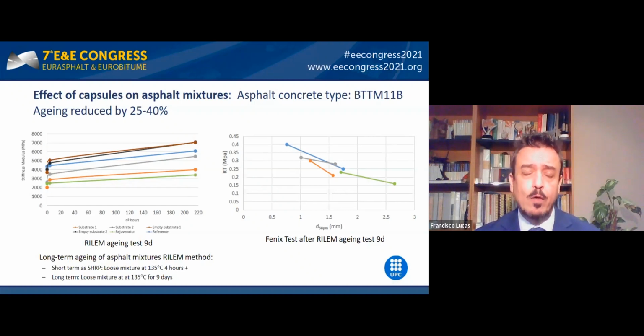by the Polytechnic University of Catalonia in Spain for the performance characterization of bituminous mixtures, correlating the deformation and resistance of the mixtures at different temperatures. And the results again show a behavior consistent with blends that contain regenerators in capsules and those that don't have them.